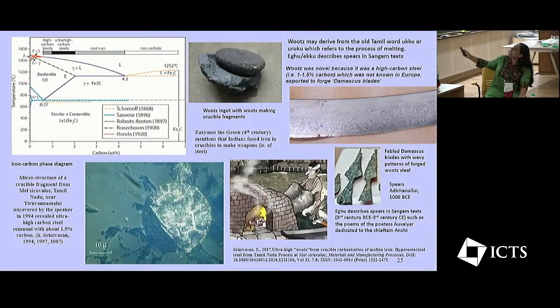And now what is interesting is that this term wootz itself is derived from the Tamil word ukku or urukku, which refers to the process of melting. So here what was happening is that the wrought iron was being carburized in crucibles so that it reached the liquidus really. So at very highly reducing conditions, the liquidus is reached here. And in this viscous condition, the wrought iron was being packed with very carbonaceous materials like leaves and wood and so on. And through that, the wrought iron was being carburized to give high carbon steel here.